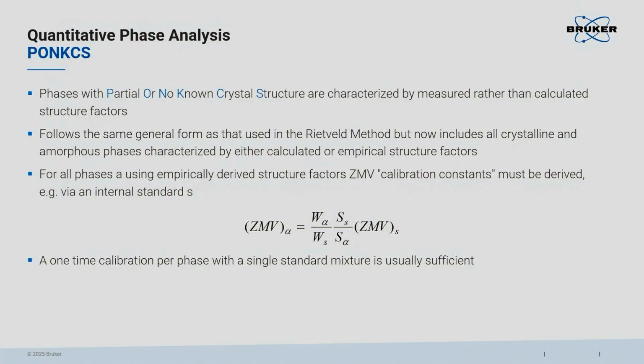It has the disadvantage that you have to do a one-time calibration. You have to do some spiking. Usually, you have to do this only once, at least only once for one wavelength. It will normally provide you with the most accurate results, because all the typical structure-related errors are cancelled out in the PONKCS method, because you use observed intensity distributions. But as I said, we do this tomorrow, in the next session.